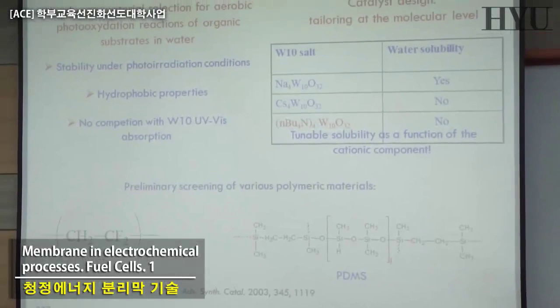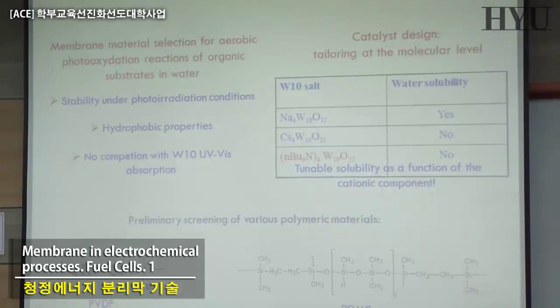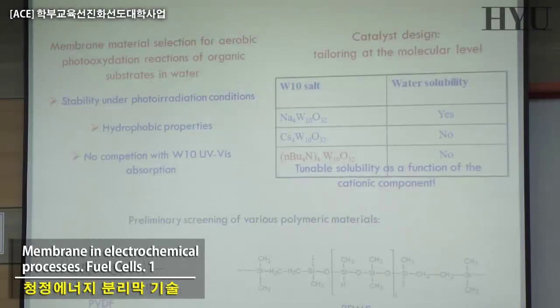The membrane material: the first thing when you are doing this kind of work, you have to check the conditions that you have to respect to be sure that the catalyst can operate. In some cases, when you immobilize your catalyst, you can completely destroy the possibility, for example, that the system is stable. So you have to check the stability under the irradiation condition to see if the catalyst will work. Eventually, which kind of properties are necessary in terms of hydrophobic or hydrophilic for the kind of reaction. In this case, it was a reaction of organic substrates in water, so the hydrophobic properties are one of the aspects that you have to check.